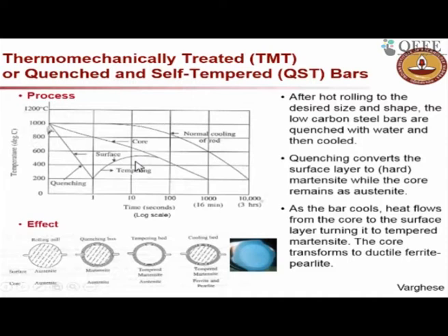How is this made? You have this time log scale here, and then you have temperature. When the steel is being manufactured, you put the steel through a quenching process. You quench the steel in about 1 second, so 0 second, 1 second here. You reduce the temperature from 1000 degrees to around 200 degrees, and then allow the steel to slowly cool. In this process, what is happening is it slowly comes to the normal temperature, or we call it tempering.